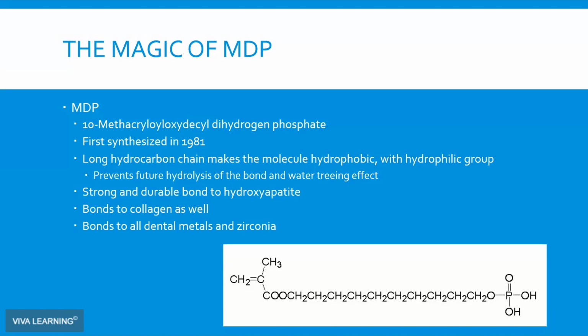It also bonds to collagen, so I noticed that early on too. When you used a little too much MDP-containing adhesive on the soft tissue sometimes, and then somehow floated a little composite on there, often it was very difficult to remove. I found that interesting. And of course, a key feature, a selling point of MDP, is that it bonds to all the dental metals, and the timing of it couldn't have been better. It's a tenacious bond to zirconia.